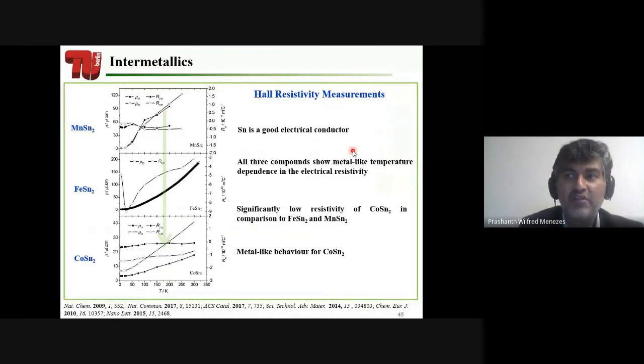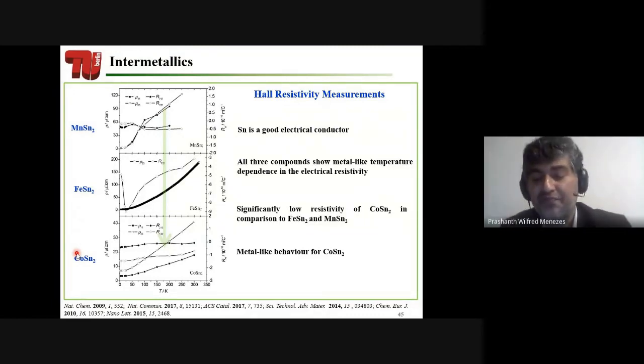Okay, the first thing which came to our mind is we have to use a very highly conducting material, because conductivity is a very important aspect for water splitting. And we looked in the literature, and we saw that all these materials are very conducting. And from this we concluded that cobalt tin is very conducting, because there has been a report in physics that they compared all these materials and showed that cobalt tin is the highly conducting material, and it also has an active center which is cobalt. So we thought, why don't we try this material for water splitting?